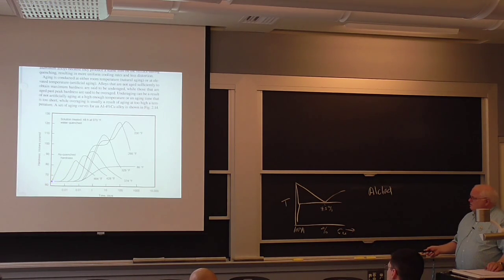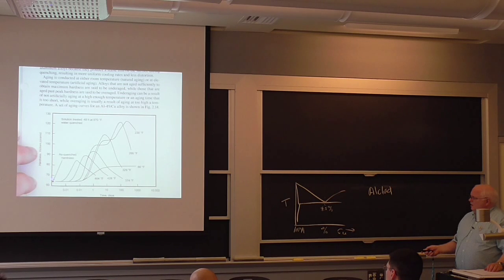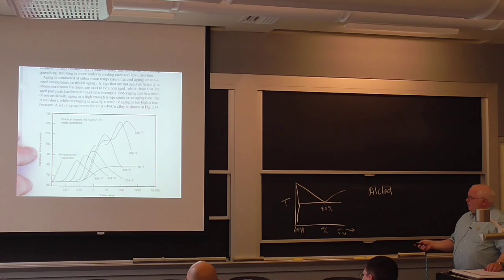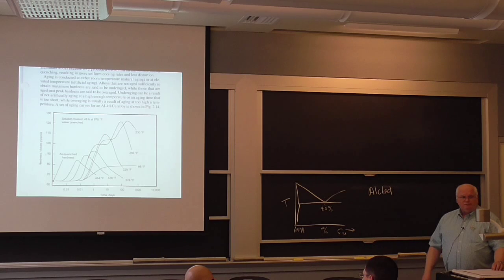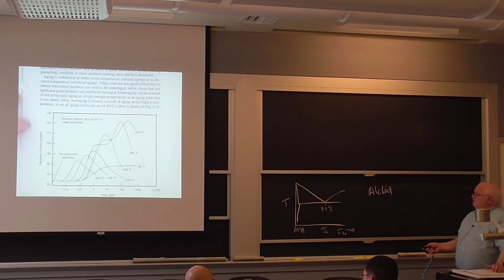The as quenched hardness is way down here at solid solution, and this is an annealed product. Okay, it's dead soft. And if you just leave it at room temperature, after an hour it starts to harden just naturally as the precipitation takes place even at room temperature. After 10 hours you actually reach a significant increase in strength, and that will go out to hundreds of thousands of hours, which is 10 years, okay, or 20 years.